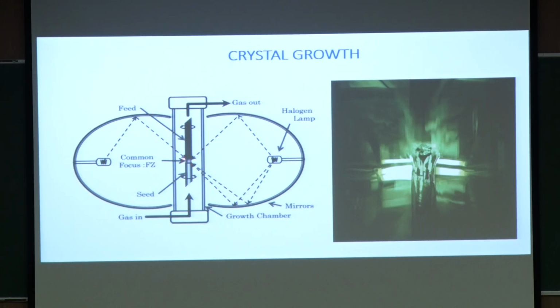So there you melt, and this is the kind of melt that you get, and then what you do is you move both of them down simultaneously at a very slow speed, and what that does is that it transforms this dull looking part into this shiny looking part, which is the crystal. So which is what you see here. This is the rod, which is just a compacted powder, and this is actually the crystal which is coming out of this compacted powder when you run this process over many days.